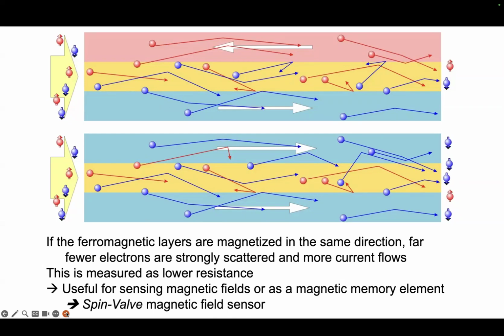And it turns out that, and again, I'm not going to discuss all the details, if you create structures in which you control the orientation of these magnetic layers, then you can, in the presence of tiny magnetic fields, change the resistance of this device as the magnetic moment of one of these layers is redirected by the external magnetic field. And even today, this is one of the most sensitive detectors of small magnetic fields at room temperature. It's based essentially on these nickel-based layers, but the interfaces actually are where the scattering takes place.